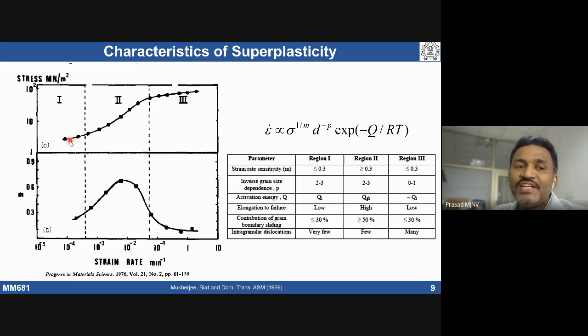So region 1 can be diffusion creep. Mostly it will be associated with a diffusion creep mechanism. And in region 2, the dominant mechanism is grain boundary sliding. The dominant mechanism is grain boundary sliding.